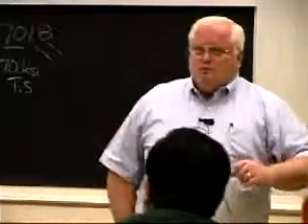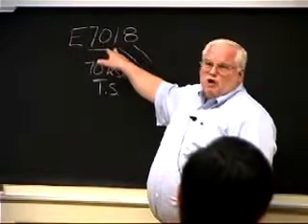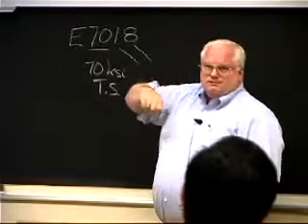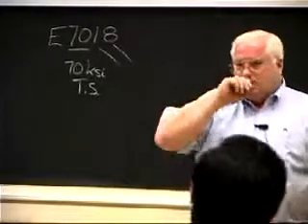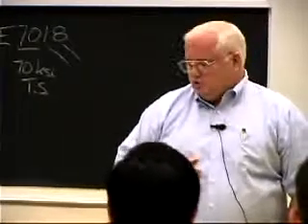Yeah, vertical. There's a 7028. Well, a 1 usually means it can be used in all positions, okay? But a 2 restricts you to certain positions, and you just can't weld in certain other positions. The arc is not stable in those other positions.